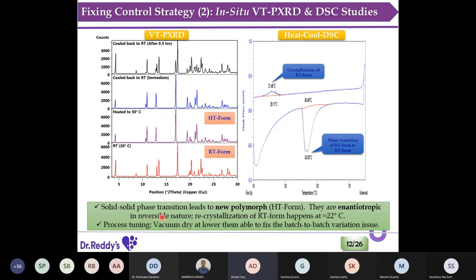So from this, it's very clearly understood that a solid state phase transition leads to a new polymorph, which we call the high temperature form. And it is enantiotropic and reversible in nature, and it recrystallizes around 22 degrees. That means, so what control strategy can be taken as a process tuning?